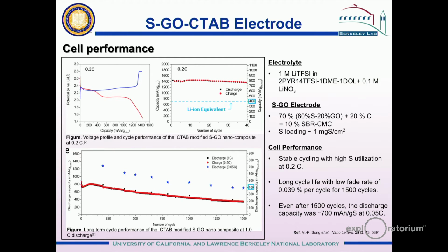And so in our early work, we used sulfur loadings of about 1 milligram of sulfur per square centimeter of electrode area. And these plots show some of our experimental results. This is the discharge curve, the red curve. And here is the charge curve, the blue curve. And we want these curves to be as close to one another as possible, giving us very high efficiency.